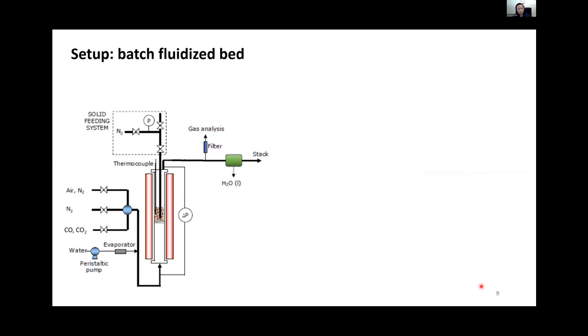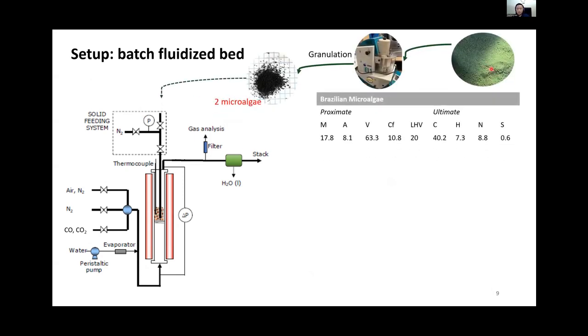So we used the batch fluidized bed to test the candidates, the oxygen carrier candidates. The batch fluidized bed has a gas preparation system, a high temperature reactor tube, a fuel feeding system, and a gas analyzer system. The microalgae are from Brazil, but when they are received, they are fines or powders smaller than 10 microns. This is too small, we cannot use this powder in our system. So before we use it, we granulate with a granulator and sieve to 200 to 400 microns.